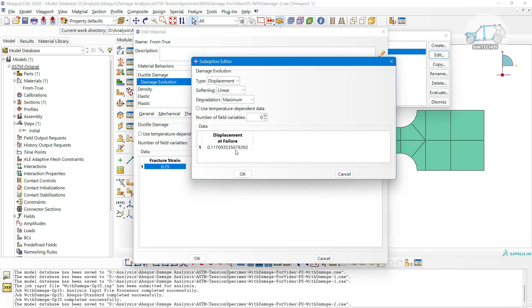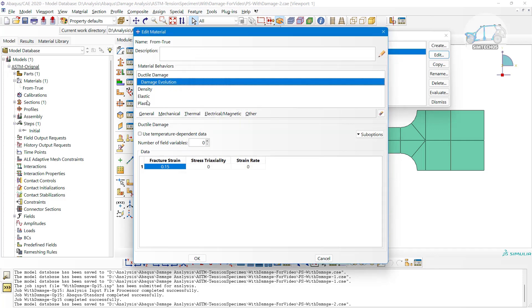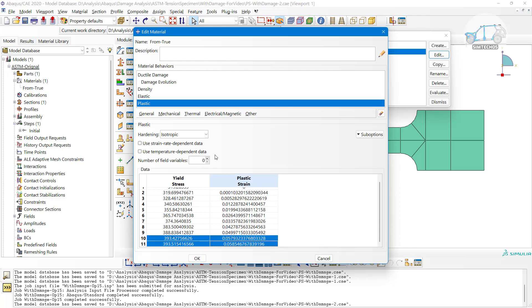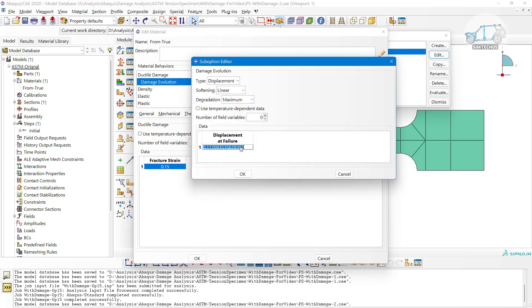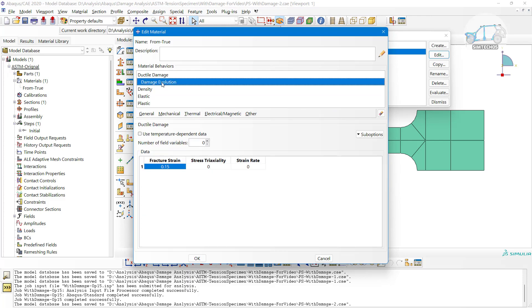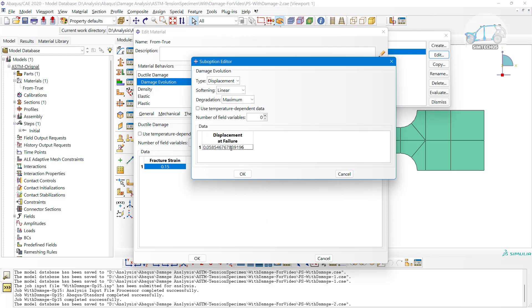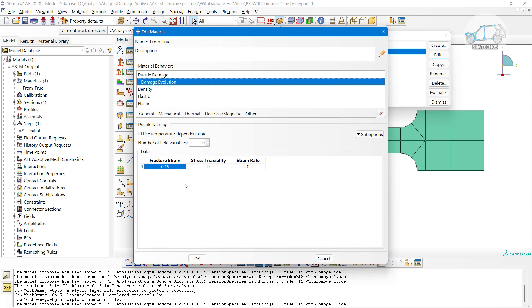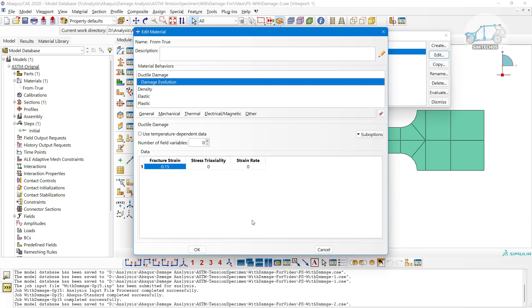The displacement at failure is exactly twice the plastic strain, not thrice, because displacement at failure equals plastic strain multiplied by the characteristic length of the element, and here the characteristic length is 2. You can directly copy the maximum plastic strain value, go to damage evolution, paste it, and multiply by 2 - that's the characteristic length. The value will be automatically modified. Next, you must define a proper value of the fracture strain.